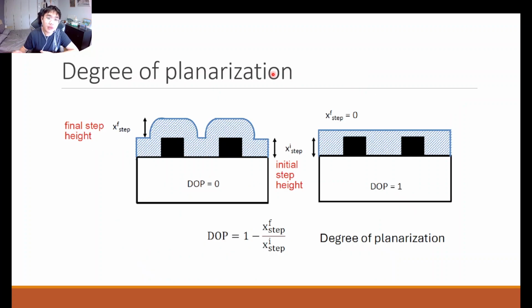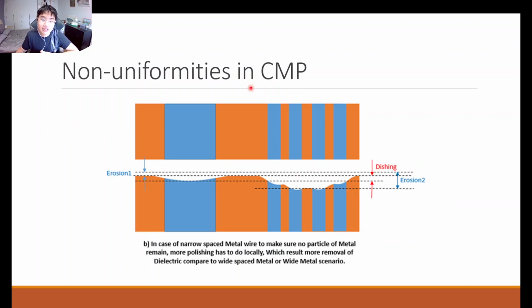And so how do we define our planarization properties? We have this idea called the degree of planarization that tells you how planar your surface is after the CMP process. It's very simply 1 minus your final step height over your initial step height. So imagine if it's perfectly planarized, there are no steps at all after your planarization, so your final step height is 0. Then your degree of planarization by definition will be 1, which indicates a perfect planarization of your wafer surface. Okay. However, CMP can also result in non-uniformities.